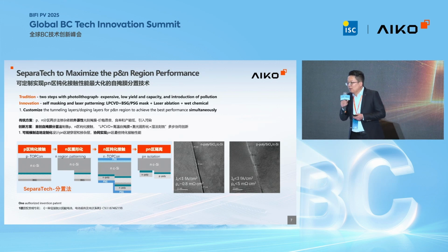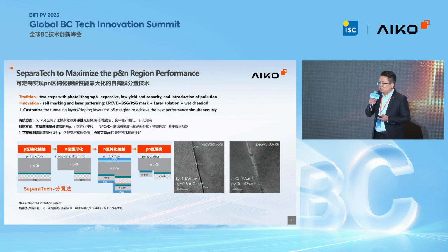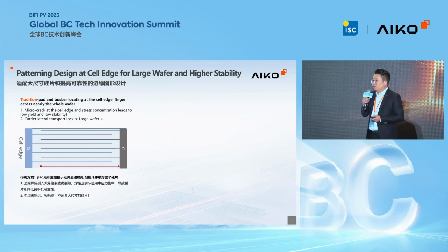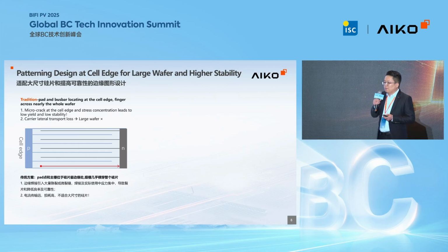And then we diffuse the doping and form the P-type contact. We systematically study the LPCVD, laser patterning, and wet chemical processes. By synergistically optimizing the three processes, we are able to achieve the best performance for P and N type regions simultaneously. So if you still remember, the IBC solar cells are usually quite small, 125 millimeter by 125 millimeter.